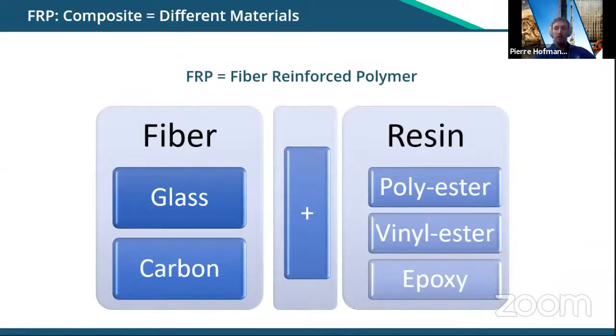So looking from a supplier point of view, I mean, Dextra as a manufacturer, as a supplier of this solution, we really have to see that those elements, fiber and resin, they are our raw material the same way a steel mill will be able to play with the chemical composition, playing with the carbon content, playing with the other chemical elements, manganese, phosphor, to create a ductile steel, a high performance, very high strength steel, or to produce stainless steel. The same way, by selecting the right fiber, the right resin, and together with the right process, we can give very different properties to the FRP product. During this presentation, we will mostly talk about GFRP, G again standing for glass fiber reinforced polymer.